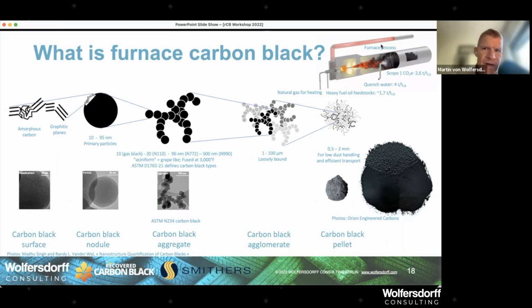On top of the right-hand side, you can see a furnace reactor. This picture is from Orion Engineered Carbons. And so you put in very hot air, that's the red here. Then you put in natural gas or methane for heating. And then you have a long nozzle, which is injecting the primary feedstock, the heavy oil feedstock.